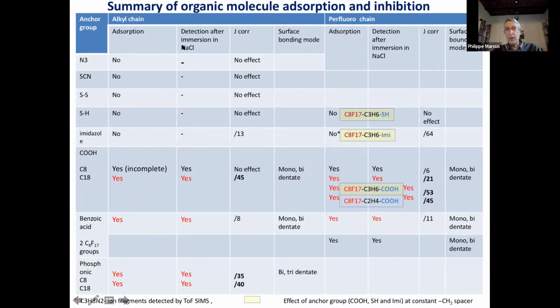And the second column is whether we detected these molecules after immersion in sodium chloride. So obviously not in the case where they were not adsorbed from the beginning, but in these cases where you have the yes in red, we would expect, if we have adsorption and even detection after immersion for 6 months in chloride solution, an effect on the corrosion inhibition.